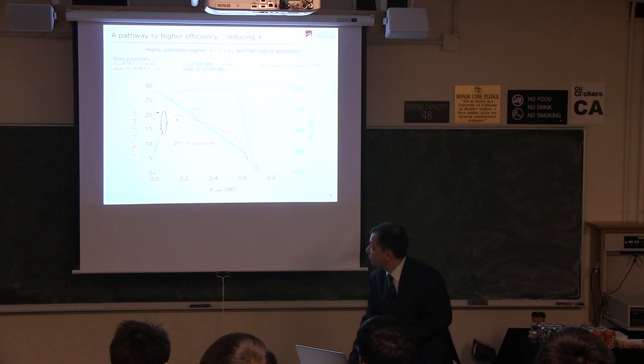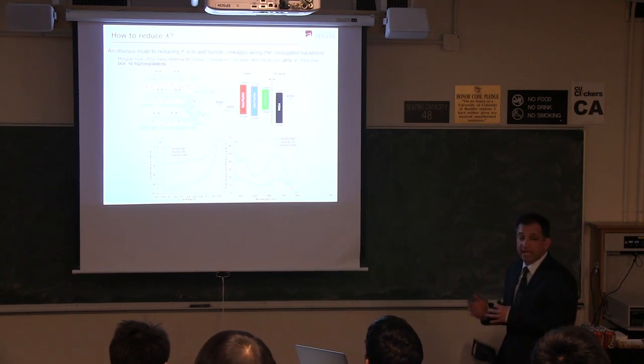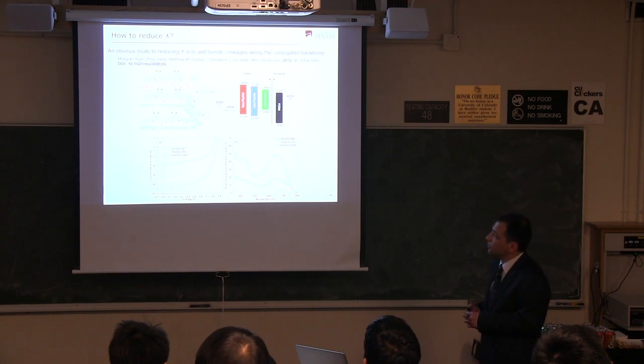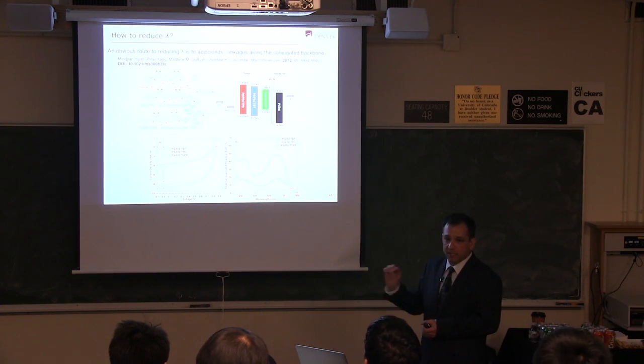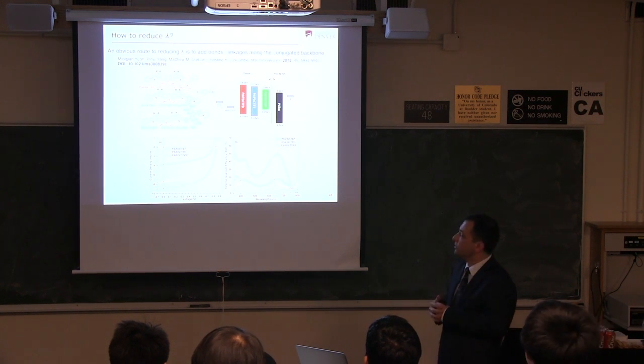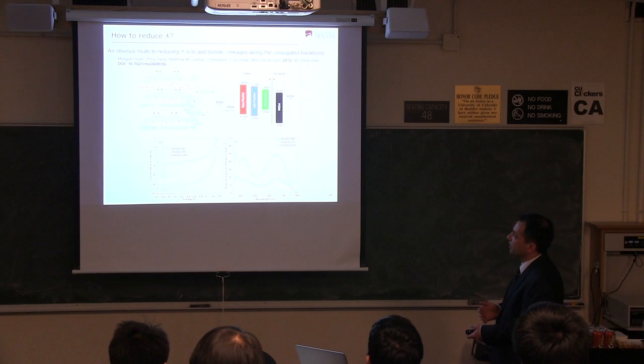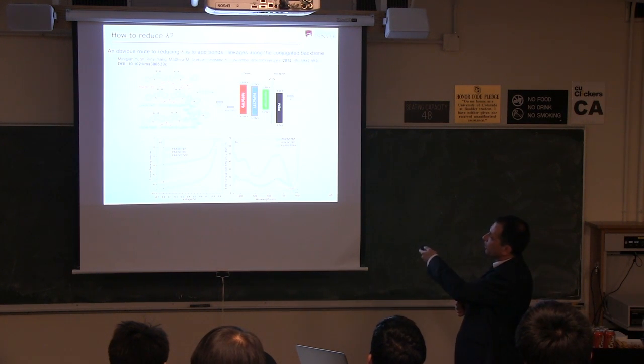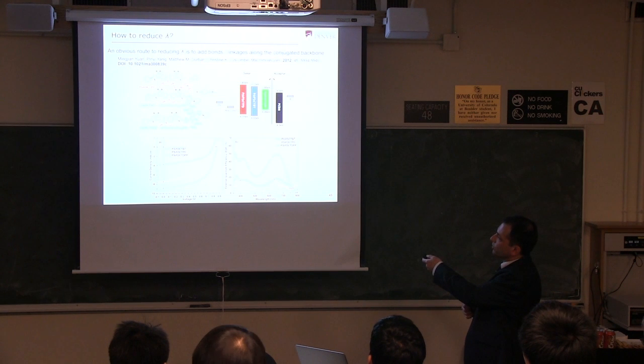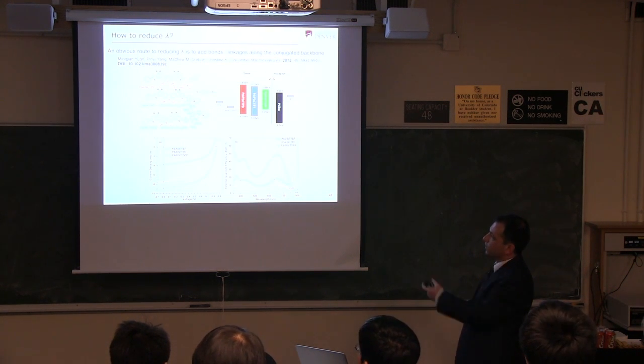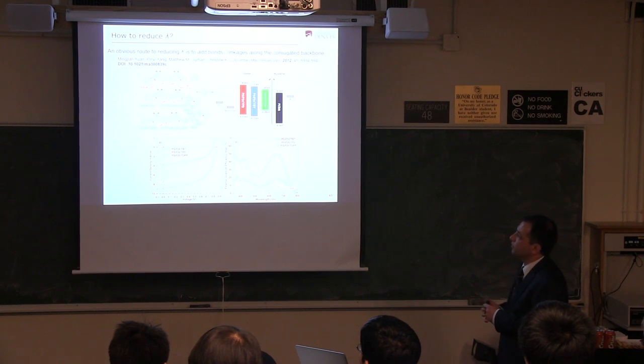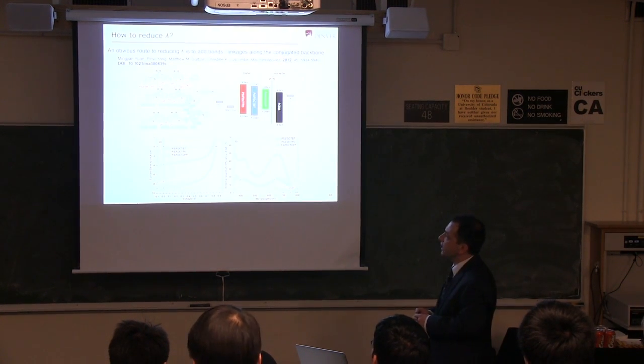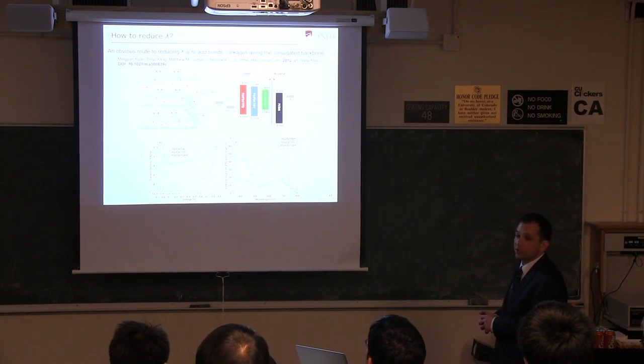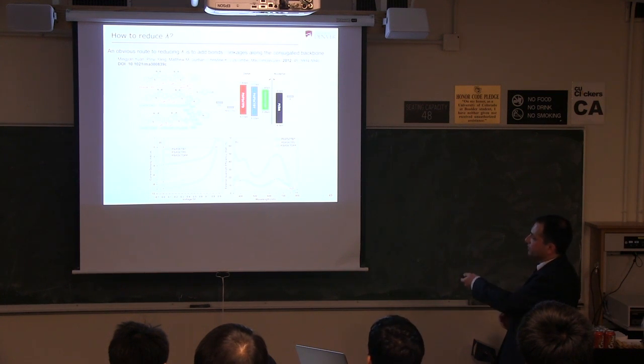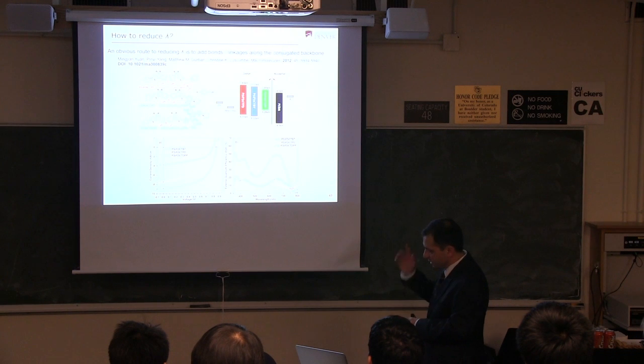Okay, so I just want to wrap that discussion by saying we have some candidate materials that might do this. The way you would do this would be to put in lots of cross-linked bonds inside the polymer and make the backbone very rigid. And so we have such polymers that have been given to us by Christine Luscombe's group at the University of Washington. So they are these sort of heteropolymers that have really long conjugated segments where there's lots of bonds on both sides of the backbone. So we don't know the reorganization energy of these guys, but we assume they are a little bit lower, a little more rigid, and we could try pushing the band offsets lower. And by the way, she can tune the band gap across several different spectral windows with those materials. So still working on that.